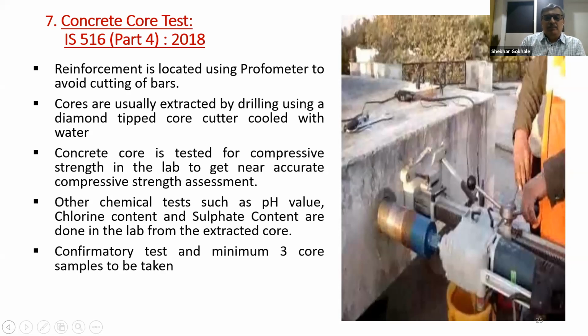And after crushing the core, other chemical tests such as pH value, chlorine content, sulfate content, etc., can be done in the lab. So this is a confirmatory test, like a cube test. This gives the actual compressive strength of the member which was constructed some time back. The rebound hammer test and ultrasonic pulse velocity test can give erroneous results sometimes, but this is a more accurate test, and we can rely on it.